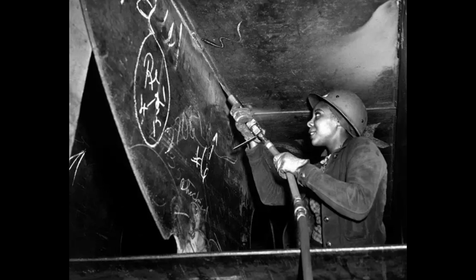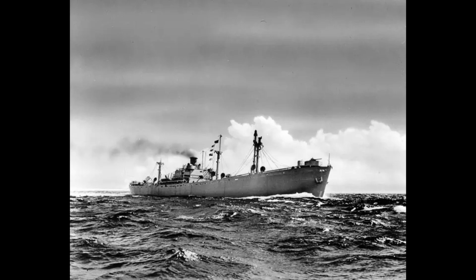52% of serious Liberty ship fractures originate at hatch corners. The hatches have square corners, classic stress concentrators. Naval architects have known for decades that corners concentrate stress and should be rounded. Liberty ship hatches are square because the design is simplified for rapid production. The corners meet welded seams. The combination creates perfect crack initiation sites.